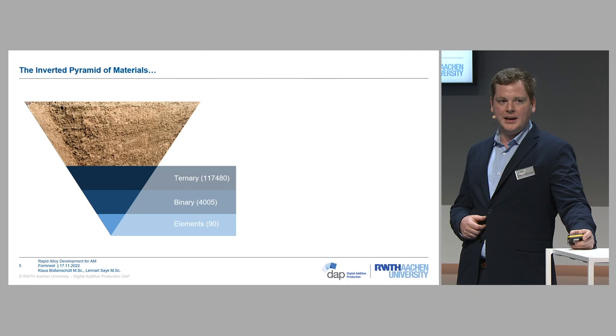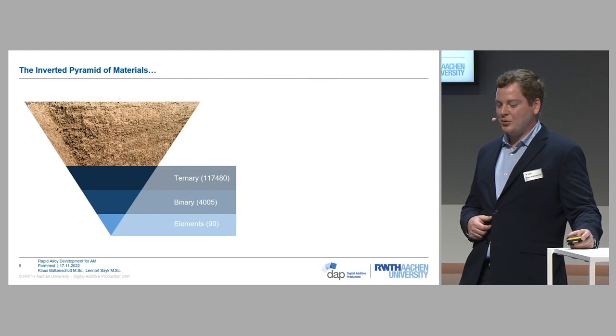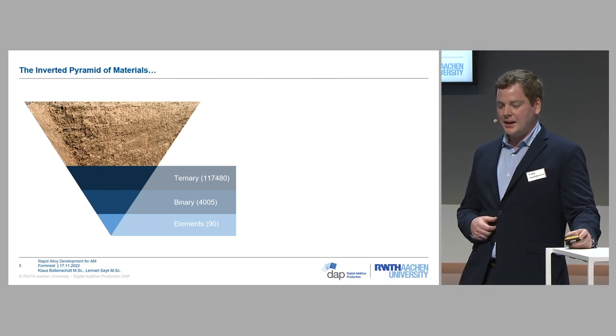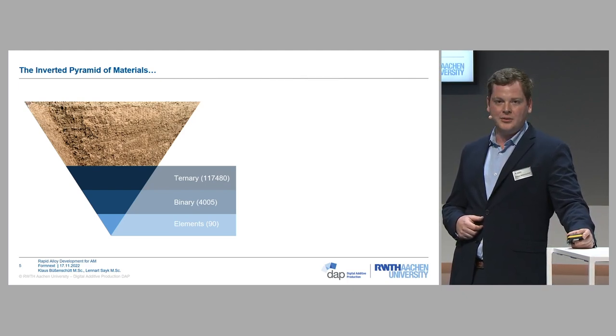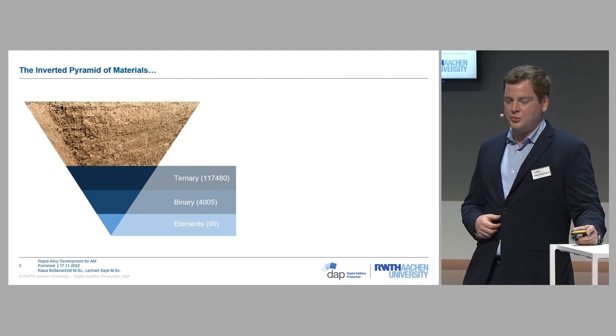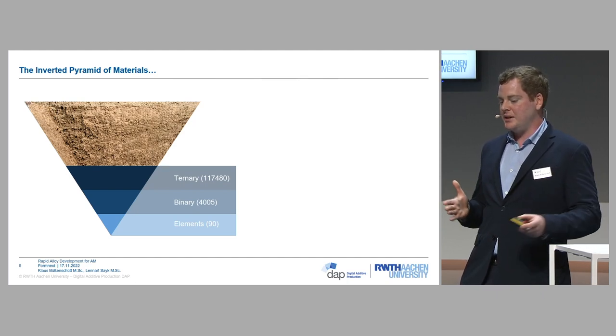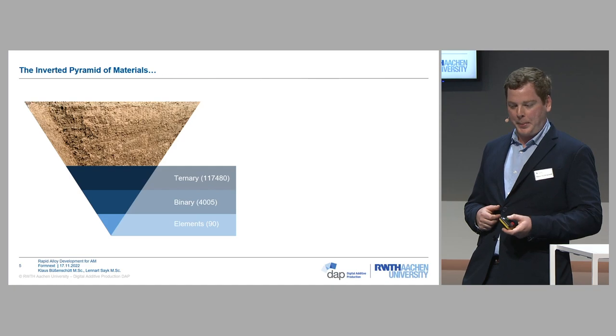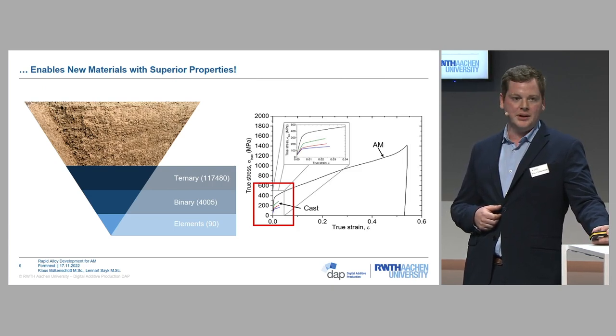Why is it so challenging to develop new alloys for additive manufacturing? If we take around 90 processable elements into account, just making a mixture of two different elements gives over 4,000 different combinations. With three elements we have over 117,000 possible combinations, and this goes on and on. With alloys of 10 or more elements there are enormous numbers of combinations to screen. What we want to achieve is materials produced with AM that have superior properties compared to conventional processing.